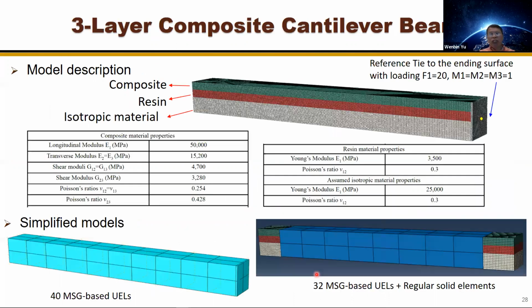And we did a very simple example, a three-layer composite cantilever beam. And we have a complex loading at this end and the cantilever here. And it's made of composite resin and some isotropic material. And of course, this is simple enough. We can use hundreds of thousands of elements to do the three-dimensional analysis. We can also simplify in such a way, using 40 MSG-based UEL only.